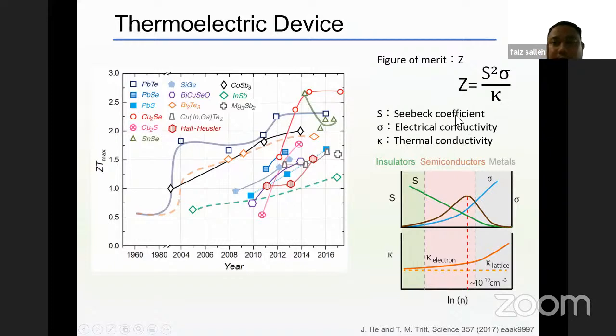So we go back to the figure of merit. We know that these material parameters strongly depend on each other. If we increase the Seebeck coefficient, we will decrease the electrical conductivity, and it will also affect the thermal conductivity. So usually, if we plot the relation between the Seebeck coefficient, electrical conductivity, and thermal conductivity, we need to find the optimum value to have a good thermoelectric material. It is reported to lie in semiconductor materials that are heavily doped, with high carrier concentration, around 10 to the power of 19.